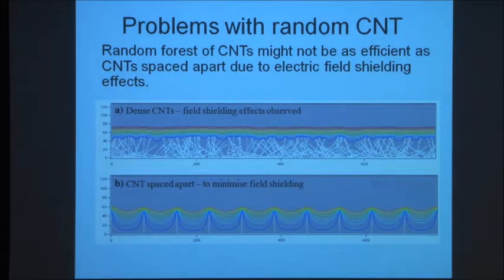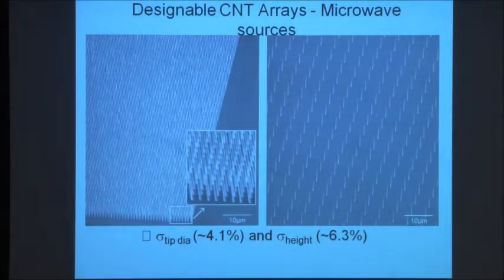So that's why we got this new technique for growing the CNTs, to make them all the same height and the same distance apart. If you make them about 2 times their height apart, then you'd get no field screening. And each one of these emits. And by doing that, you get more current emitted. And for some applications, that's what we need. So that's why we needed to design these arrays of CNTs.